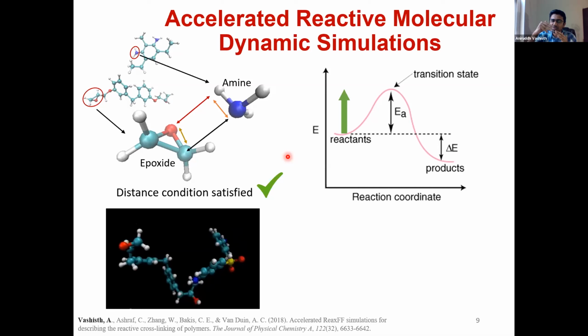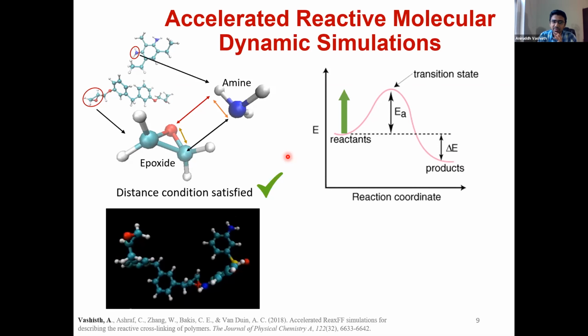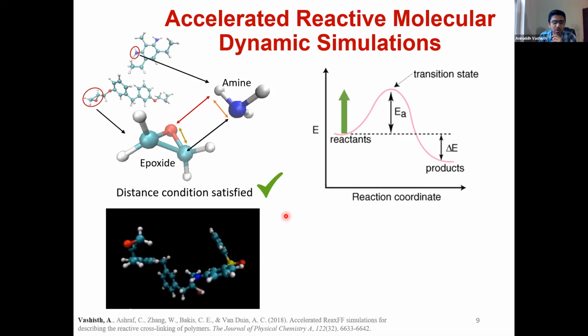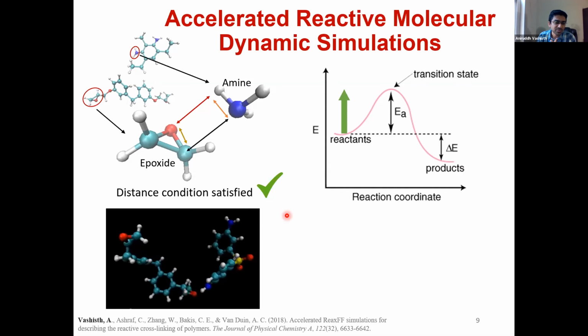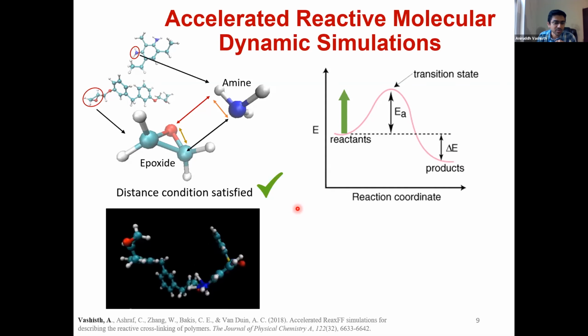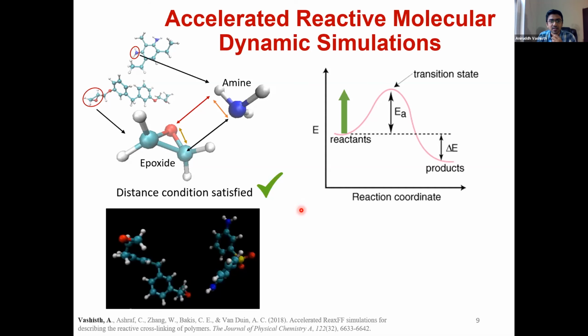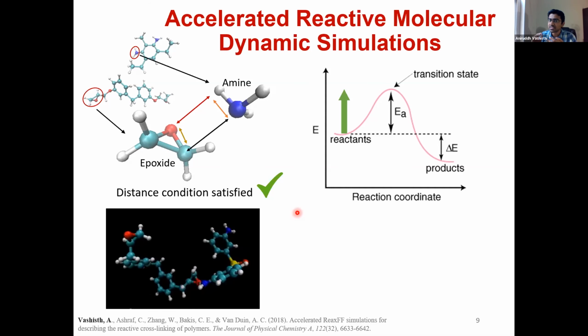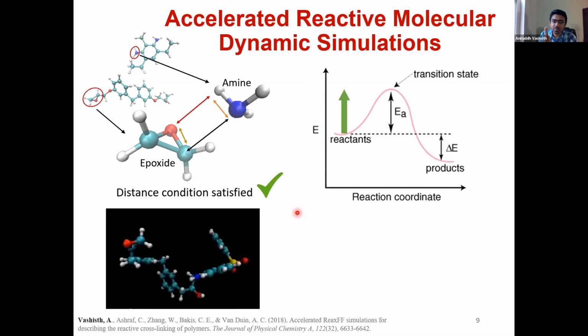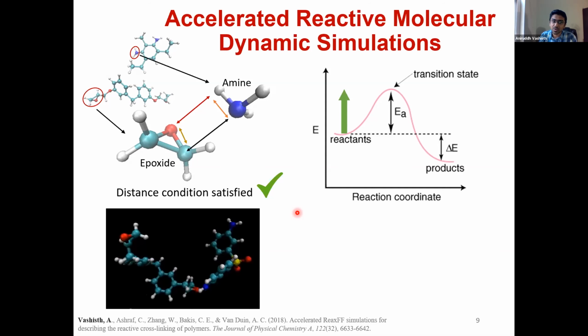If the path of approach is really nice, they react. So for example, in the video that you see here on the bottom left, you can see that the path of approach was really nice and the molecules were able to react with each other. There could be times where you would have some sort of steric hindrance, you would have another molecule in between, and in this case, you would not see a reaction.